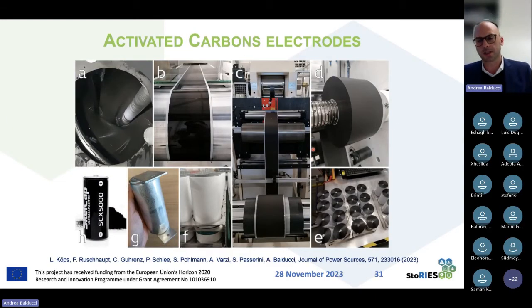And what you are seeing here is how we are bringing this material into a real system. We are taking the carbon, which is a black powder, mixing it with the other components, so with the conductive agent and the binder, to realize a slurry. Then this slurry is coated over an aluminum foil, as we said before, and calendered. So these composite electrodes go through the typical processes that are applied to any kind of electrode of a lithium-ion battery. So double coating, calendering, and then, as you see here, they can be rolled, and then you can take this electrode, use the shape that you want, and realize the sandwich, the layer structure that we were seeing before.